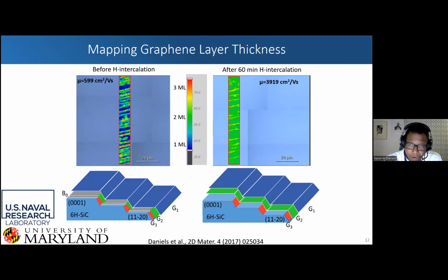Then we can look at Raman mapping. This is mapping the 2D full width at half max peak, which you can attribute to the number of layers. In this case, around 30 to 35, we generally have 1 layer. In this green-yellow range is generally 2 layers, and then the red range is 3 layers. As shown here, this is taking one sample and then intercalating it after the fact. We've gone from 600 centimeters squared per volt second all the way to close to 4,000, and you can see the surface uniformity has improved